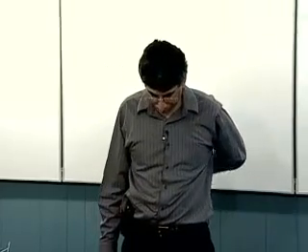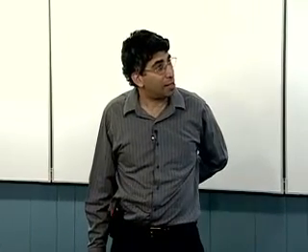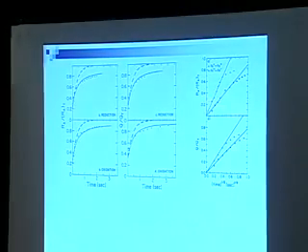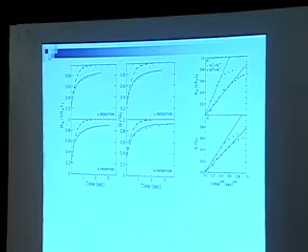And for surfaces, as they get thicker, things tend to be further apart, so you expect the self-exchange to go slowly, and so this virtual diffusion works. So now, having argued that this is the case, I go and fit my data to the Cottrell. I'm making plots of charge versus t to the 1/2, or reflectance versus t to the 1/2, one for the oxidation, one for the reduction. And it doesn't work, you'll notice.